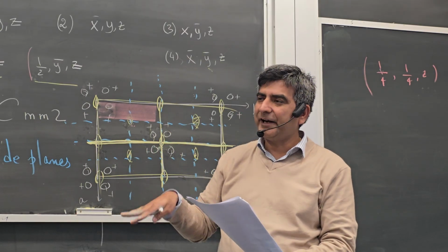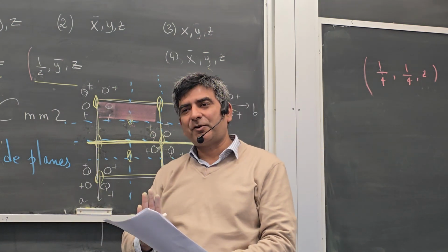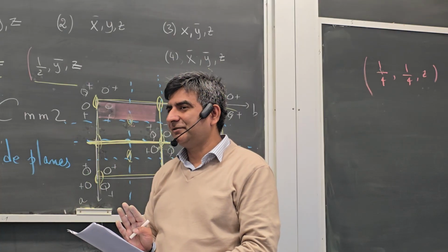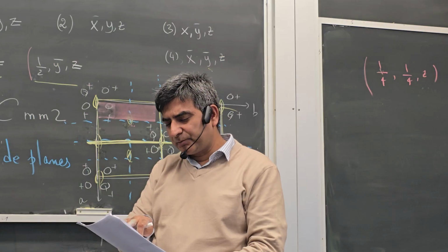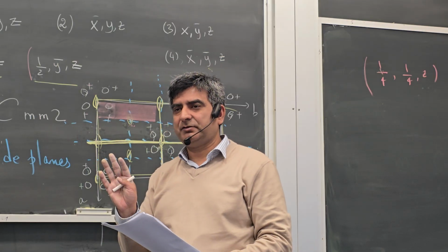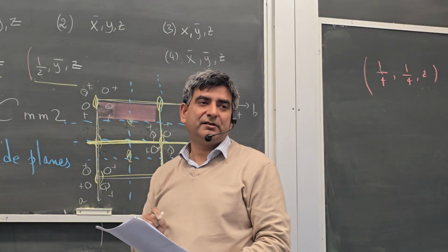And you don't want to write all 8 of them, you just write 4 of them and assume that the other 4 are from an offset, the centering offset from the origin. So you get a multiplicity of 8. So if there's an atom at the 8f position, all 8 of those positions must be fulfilled.